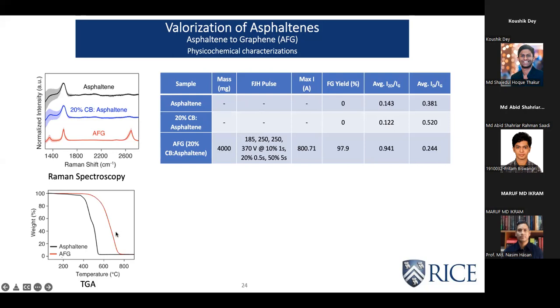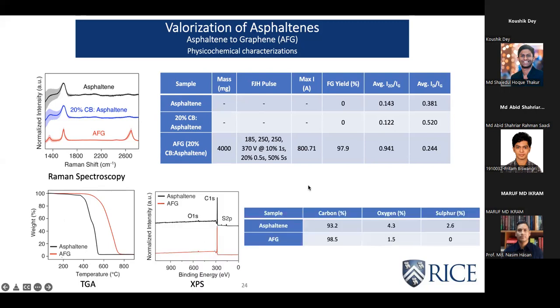We did TGA, thermogravimetric analysis. Asphaltene usually degrades at around 550 degrees Celsius, but graphene in general should have a lot more thermal stability. So when we did the TGA on the asphaltene-derived flash graphene, we got a very well improved result. We also looked into the XPS for elemental composition. As you can see, from asphaltene, the carbon content went from 93% up to 98%, and the heteroatom percentages decreased significantly.